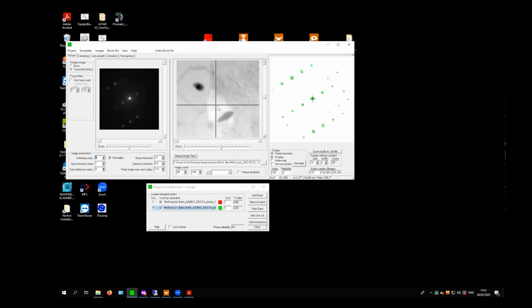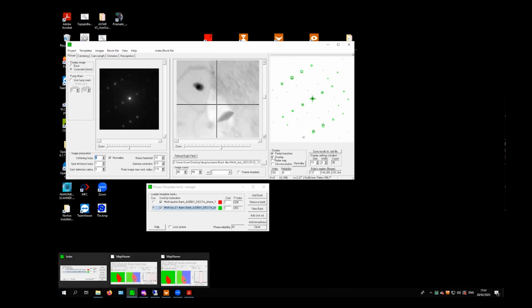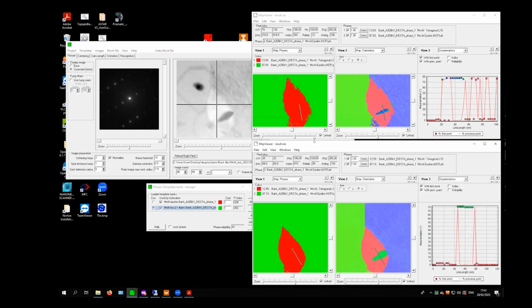What we can see is that we have a very big epsilon phase grain here on the left, and we have another big epsilon phase grain here on the right. And between these grains, and this is actually quite amazing to see on the material scientific side of things, right at this grain boundary in the current annealing step, a tau phase grain was formed. And there's a little more features inside here. And I would be able to now just also run the indexing. But again, for the demo, we also have the analyzed data here, so it's a little quicker. And maybe it's hard to see